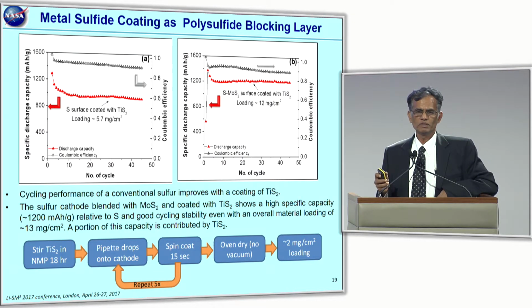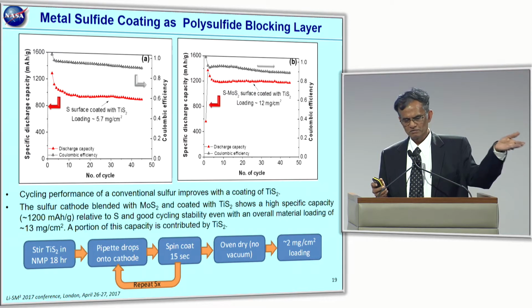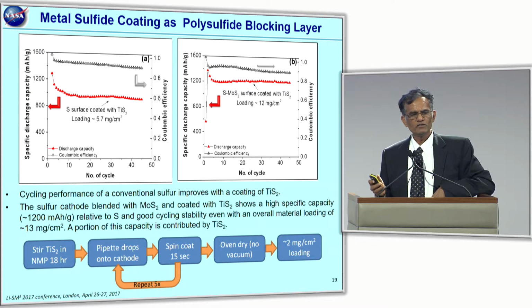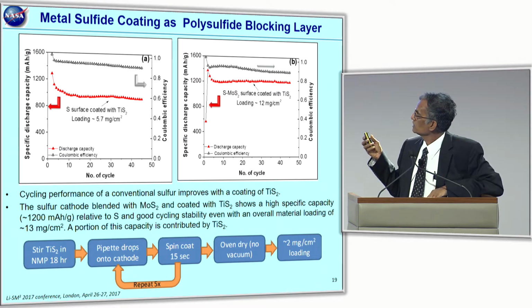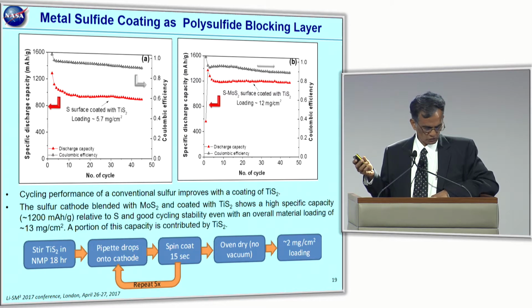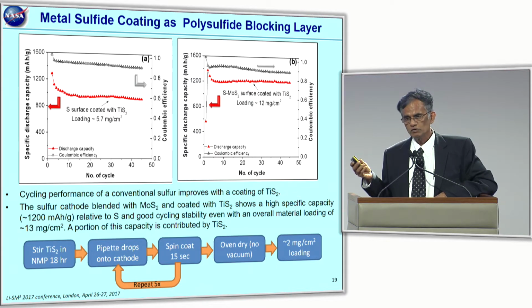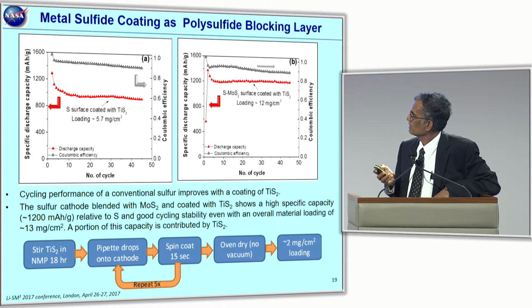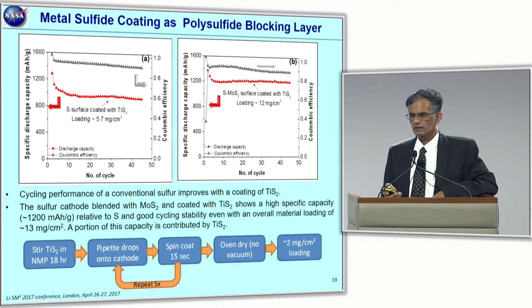And not only by way of blending it in the cathode, the metal sulfide also works as a layer. You heard this morning from Narayan about cobalt oxide working on that. Likewise here, the only difference is that this layer of the TiS2 or moly is right on the electrode. It's coated onto the electrode. It's not separated with any separator or anything like that. But you have a thin coating of TiS2 on a simple sulfur cathode on the left here, and that actually stabilizes the unblended pristine sulfur cathode even with high enough loadings. And on the right, you can see we even tried much higher loading in a moly disulfide blended sulfur cathode. Over that, we have a coating of TiS2, and that seems to give excellent cycle life as well. The coating is done by spin coating of a tiny portion of this, or it could be done like a spray coating, or even doctor bladed like any other electrodes.